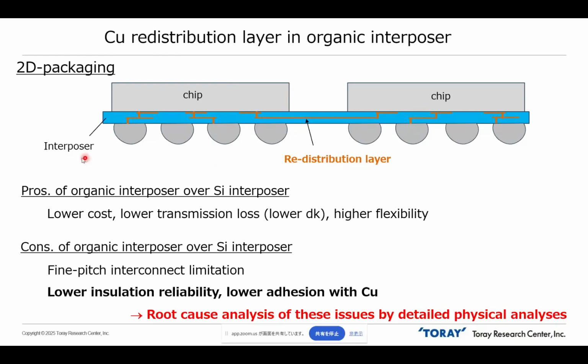There are several kinds of interposer: silicon interposer, glass interposer, and organic interposer. Organic interposer has strong points. In the case of organic interposer, we can fabricate at lower cost. Transmission loss is also lower than other types. Also, this interposer has higher flexibility. But in the case of organic interposer, it is difficult to fabricate fine pitch interconnect because insulation reliability is low. And sometimes adhesion with copper has a problem. So it is important to find the root cause of this issue.